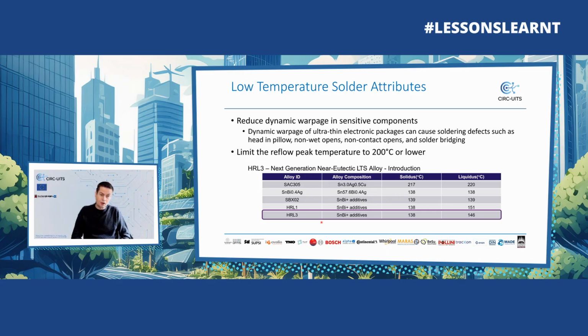The mobile industry is one, and of course all applications where you have vibration could not use low temp solder. So we, as the industry of tin suppliers, of solder suppliers, went into looking how to overcome this brittleness. And we came up with a solution of doping. Doping is a technology where you add elements to an alloy, and these additions are below 1%. But it's just enough to reduce the brittleness.